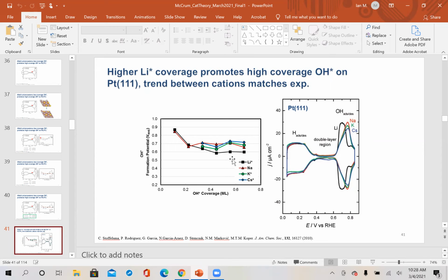But although I do appreciate the extra complexity with the extra water dipoles. Sure. Yeah, and we haven't made a quantitative comparison to that, but certainly there is overlap. But I guess one of the things is also, the penalty for cesium to lose its solvation shell would be lower than for lithium, because lithium typically has a much larger solvation, right? Yes, right. And so the solvation energy of the ions presumably also plays a role.